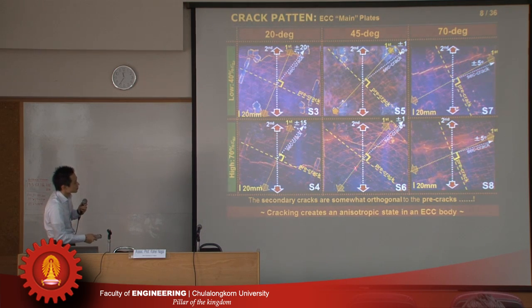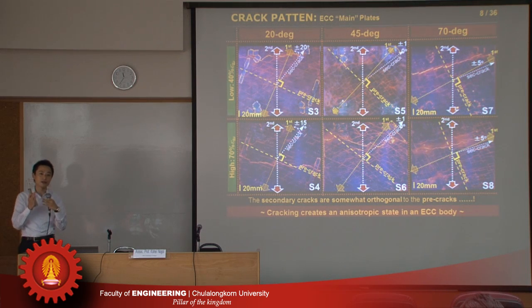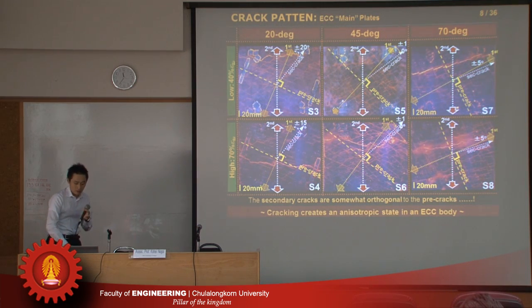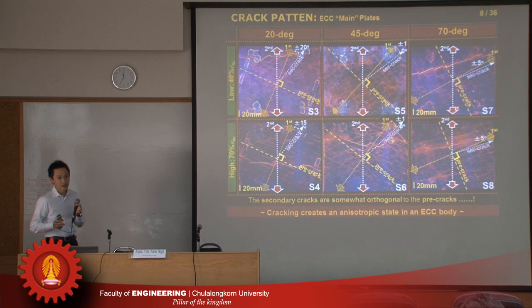For example, let's see this one, the 45 degrees case. The secondary crack should have gone in this direction, but we do not see so much of that direction. The crack is almost normal, meaning perpendicular to the initial direction. It is because this material becomes an anisotropic material because of the initial damage, and that is caused by the weak shear transfer of the first cracking. The first crack slides easily, then yes, this field becomes anisotropic. Then yes, an unexpected secondary crack occurs. So this is a scenario of the secondary crack.